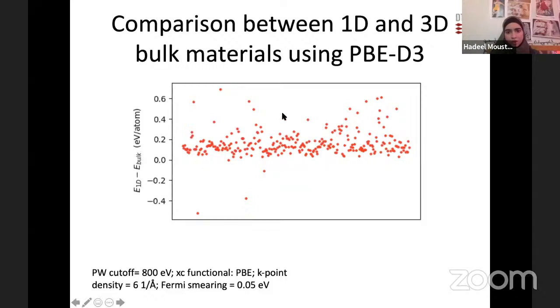So we also looked at how stable our one-dimensional materials are by comparing the energy between the 1D and its extracted 3D component. For that, we make a new calculation where we use the same computational details as in the relaxation, but now instead of using PBE as the exchange correlation functional, we use PBE-D3. And as we can see, almost all of them are ranging a bit over 0, which shows that they are slightly unstable. Because of that, we can still extract the 1D from the 3D and calculate their properties.